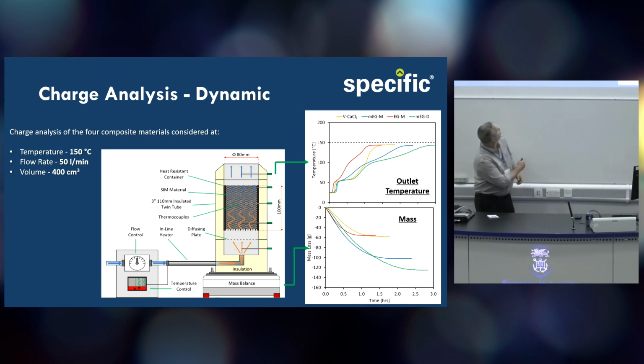So if you look at the reaction chamber we have here, this is a flow control flowing hot air through into the base of the system. We then have a material within the system and plenty of insulation around the side, which will be the ceramics and the refractories in there. And what you can see over a period of time is that as the temperature increases and the interactions occur between the chemistry and the hot air stream, the mass of the system drops down until it plateaus. When the mass is actually plateauing, that means that all the moisture has been removed and we have an equilibrium in the process. So after about an hour, in each of the cases, we're getting very close to actually removing all the moisture and charging the materials.